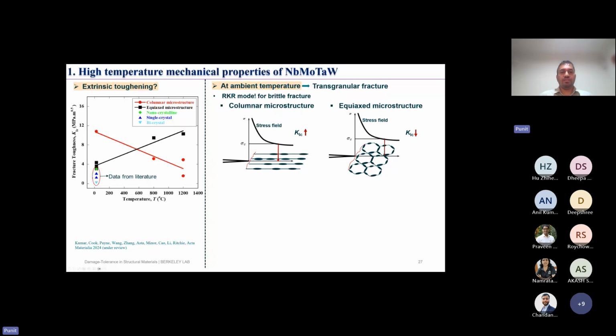So if we think of fracture at ambient temperature, which is happening in transgranular fracture mode, we can think of the Ritchie-Knott-Rice model for brittle fracture of this material. What the Ritchie-Knott-Rice model suggests is that ahead of the crack tip you have a stress field, and if the stresses from this stress field are higher than the fracture strength of a microstructural weak point ahead of the crack tip, in that case the material will fracture. And in cases where you have a high probability of finding these particles, the fracture toughness will be lower.